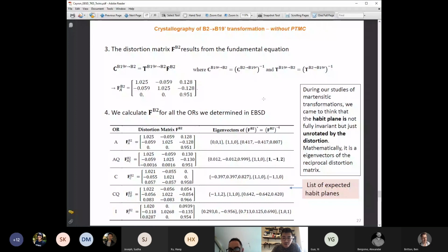So you said if you choose to show the pole figures, is it better? Is it tighter? I did not plot the pole figures here. This plane refers to indices. The Miller indices here are given in the B2 reference. It means that it's the 1 -1 2 plane in B2. Then you have to transform them into the B19 prime, the monoclinic phase. In the monoclinic phase, they are actually the plane 1 0 -1. So I should plot the pole figures on the 1 0 -1.